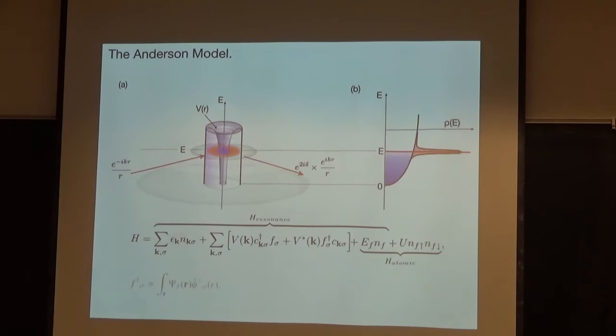And there are various things to say about it. The f state here, of course, is built up out of electrons themselves, but it's a core state. And what you do in putting together the Anderson model is that you orthogonalize the conduction electrons against this localized f state, and you then do the degenerate perturbation theory of that problem, and that gives you the Anderson model here. But then you have to add in the interaction, and that interaction is basically the Coulomb interaction between the two electrons in one shell here. This is a very simplified model, but this model already has in it the physics of the Kondo model, and I wanted to go into the discussion of how the Kondo model comes out of the Anderson model.